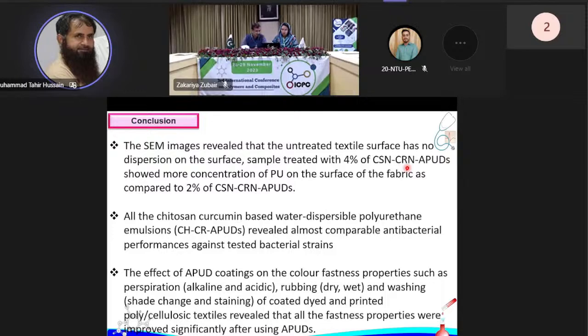And all the chitosan and curcumin-based water dispersible polyurethane emulsions revealed almost comparable antibacterial performances against the tested bacterial strains. And the effect of the APUD coatings on the color fastness properties such as perspiration, alkaline and acidic, rubbing and washing of the coated, dyed and printed polycellulosic textile revealed that all the fastness properties were improved significantly after using the APUD.